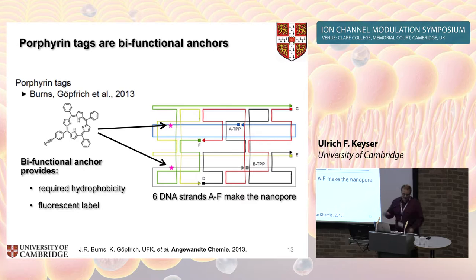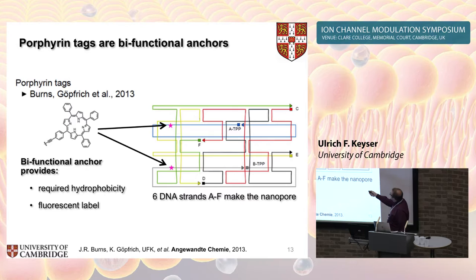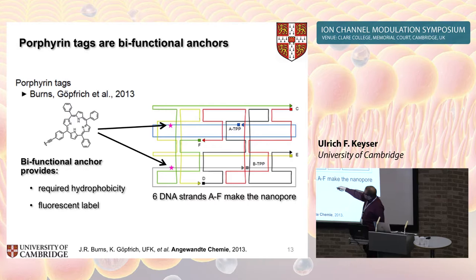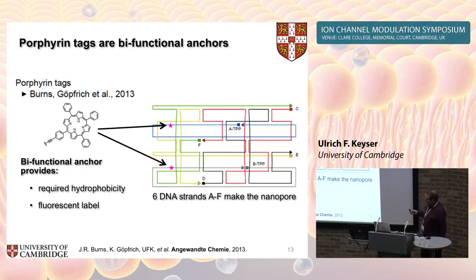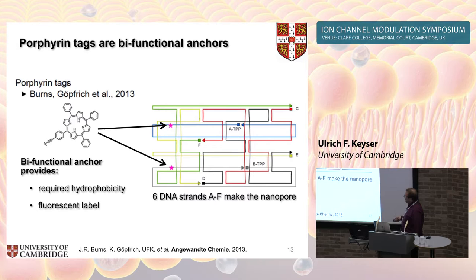How does the structure look? This is a wireframe diagram — similar to the amino acid sequence of a protein. You have six different DNA strands: green, yellow, red, blue, dark gray, and light gray. We added the porphyrin tags to specific positions to make an asymmetric channel with two hydrophobic regions. You can see this in the microscope because it's fluorescent. The nice thing about DNA is that you can characterize it easily — put it on an atomic force microscope, do gel electrophoresis to check if everything is correctly folded. These structures are very easy to verify compared to working with membrane proteins.